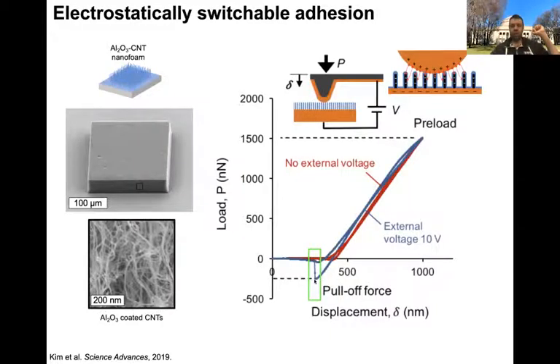And what you want to see is down here, when we're in the regime where we're pulling the tip away from the substrate, you get a much higher pull-off force because you're inducing charge between the CNTs where voltage is applied and the tip, which is grounded. And therefore, you can effectively manipulate the adhesion between the tip and the substrate, which is the CNT forest.